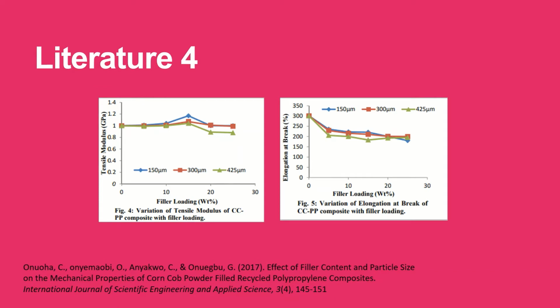For tensile modulus in Figure 4, generally, tensile modulus was found to increase with increase in filler loading up to 15 weight percent content and decreased with particle size. This could be attributed to the fair distribution of the filler in the matrix, which efficiently hinders chain movement during deformation. On the other hand, smaller particles enhance better dispersion within the matrix than larger particles. Hence, the decreased tensile modulus with increase in particle size.